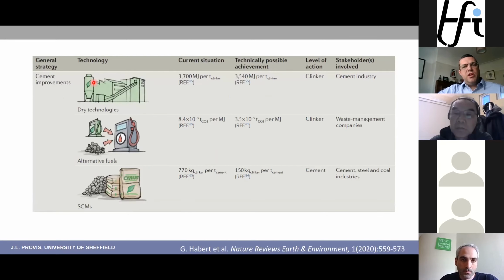We can improve the energy efficiency of clinker production. Again, I said that we're already doing pretty well. There's a bit of scope there. By using alternative fuels, we can reduce the attributed CO2 per megajoule that goes into actually producing the kiln. Blending with supplementary cementitious materials, if we can source the materials, we can reduce our clinker content per tonne of cement from a current level of about 770 kilograms of clinker per tonne of cement, but the cement being roughly 77% Portland cement kiln product and 23% gypsum and supplementary materials.